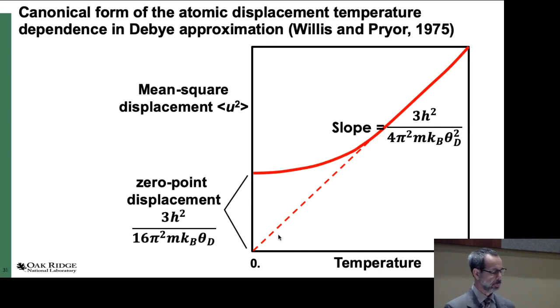So let's continue and look a little bit more at the temperature dependence of atomic displacement parameters, which is kind of dear to my heart. Here's the canonical form of the atomic displacement parameter temperature dependence in a Debye approximation. Things to note is that at high temperature it's linear, and at low temperatures it does not extrapolate to 0 temperature, but has a 0 point vibration, which is inversely proportional to the atomic mass. So, lighter elements will have larger 0 point displacements. So the temperature dependence of the ADPs can reveal information about positional disorder and other anomalous behaviors such as anharmonicity at low temperature.